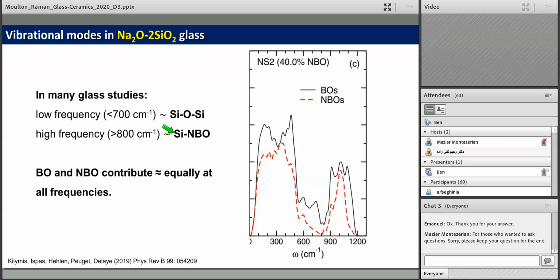These simulations, and this is consistent with my own work on a variety of crystals, show the vibrational modes divided into the contributions from bridging and non-bridging oxygen. And you can see there's a variation across the frequencies. But for any given frequency, the contribution between bridging and non-bridging oxygen is roughly equal. So these old paradigms, these old simplifications, are probably a gross oversimplification. And if we want to get to a more realistic structural model, we might need to reconsider this paradigm.